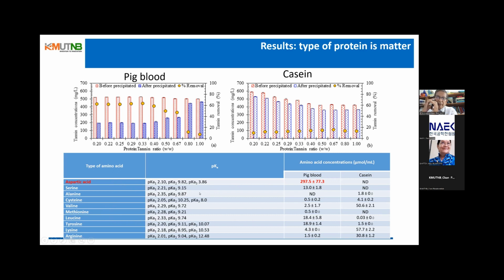And because the experimental pH is at 4, which was lower than the pKa2 of aspartic acid, the amine group of aspartic acid will be positively charged and can interact with the carboxyl group on the phenolic rings of tannins via ionic bonds. In addition, the proton acceptor of the carbonyl amine and amine groups of aspartic acid could interact with the hydroxyl groups on the phenol rings of tannins via hydrogen bonds.